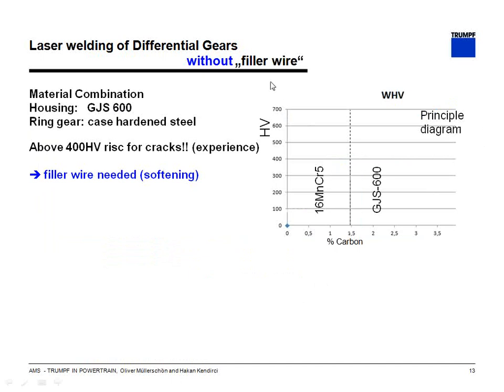Several years ago, there was an idea to weld these 2 partners, the housing here, cast material, and you can see the material GJS 600, and the ring gear, mainly a case-hardened steel, and there was the idea to weld it without any filler wire. But the problem is, it's a kind of hardening process, because the carbon content, especially of the housing, is very high, and there's a risk if we go higher than 400 HV with the hardness of the material, there's still a risk for cracks. This was the reason why mainly all the applications worldwide are using the filler wire to join these 2 partners.